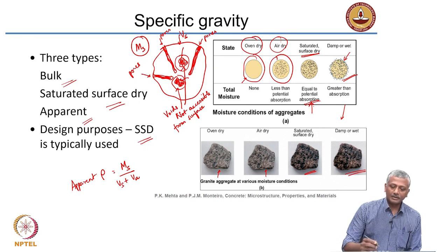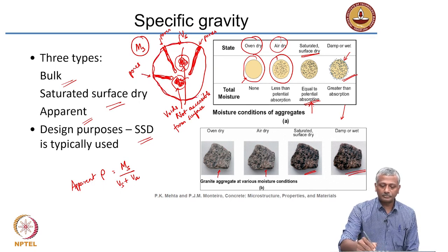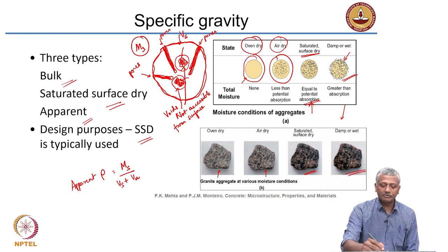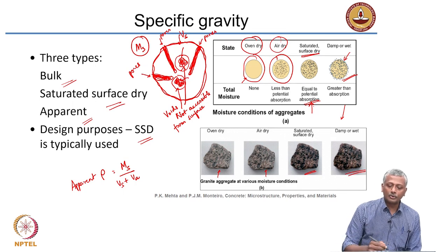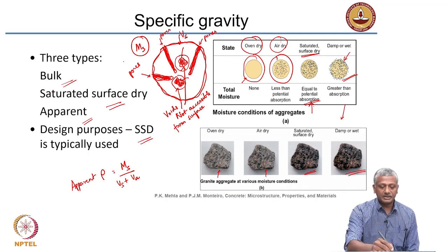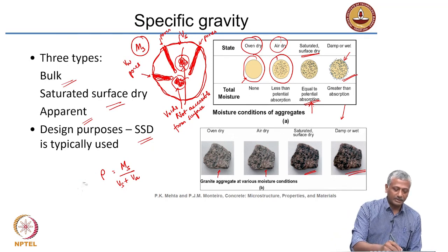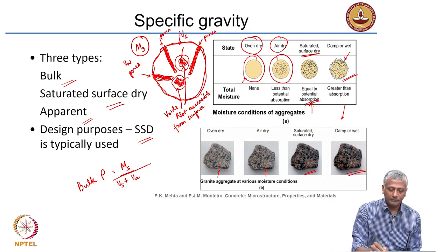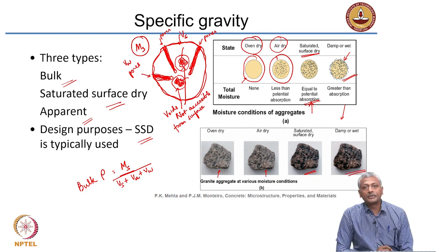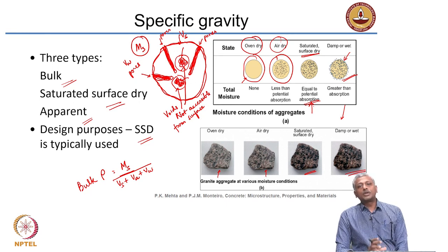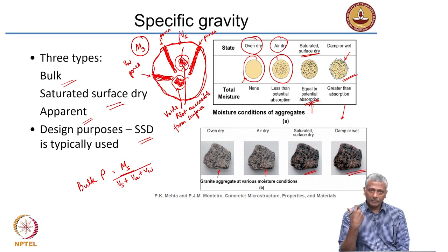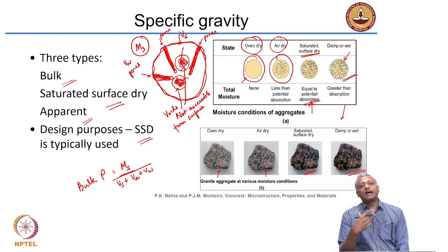What about bulk specific gravity? The bulk basically considers the entire volume, which also includes the pores accessible from the surface. If the volume of those accessible pores is Vw, then bulk density equals Ms divided by Vs plus Va plus Vw. Bulk density is the dry mass of the solid divided by the total volume of that rock, including volume of solid, volume of inaccessible air, and volume of the water-accessible pores.